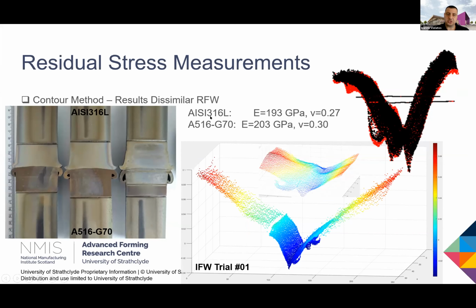We have used standard material properties for 316. Young's modulus is around 193 to 195. For 516, a standard value is 203. However, a minimum value can be down to 195. For this specific case, we selected a slight difference between the Young's moduli to see what we will get at the interface. It's not that much, however, it's still quite significant. And you can see, for example, the cloud plot from the distorted face for the first welding trial.